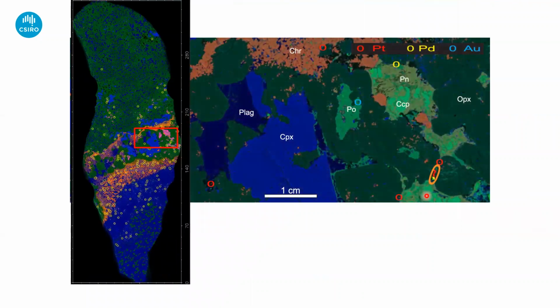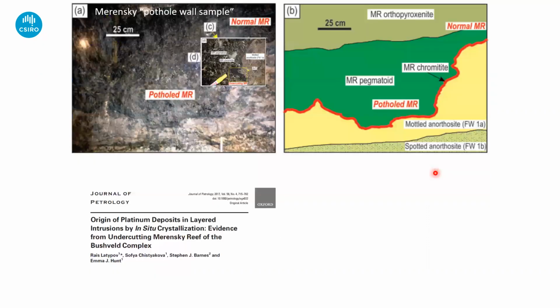One other point about this one, which is kind of interesting, there are a few big grains here. In this area, there's one big platinum grain. It's a platinum iron alloy grain. It turns out that over this entire sample, about 40% of all of the platinum in the sample is in that one grain. That's kind of a scary thought. If you're sampling these things and trying to estimate platinum grades, then you've got a bit of a sampling nightmare. And I think that problem extends through a lot of platinum group element geochemistry. Platinum in particular shows very profound nugget effects, which we're not always aware of.